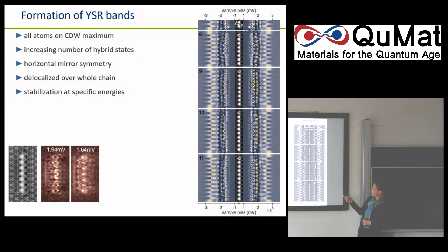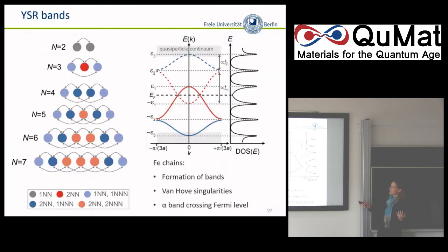Now, when you go to longer chains, you also then do not do much anymore if you put another atom. So you kind of converge to the intensities that you eventually see. But that's also kind of intuitive, right? I mean, let's say we start with two atoms, then really every neighbor that you add matters. If you think of nearest neighbor coupling and the next nearest neighbor coupling, but eventually, the next one is kind of negligible. So eventually you kind of have a bulk in the chain, and therefore it shouldn't matter anymore whether you add another atom. That's kind of the feature of band formation.